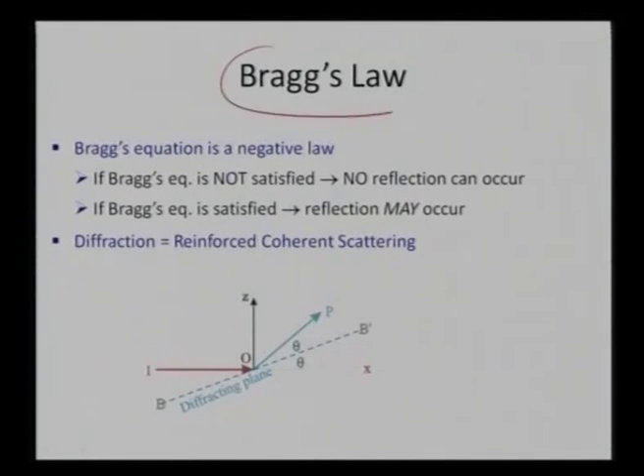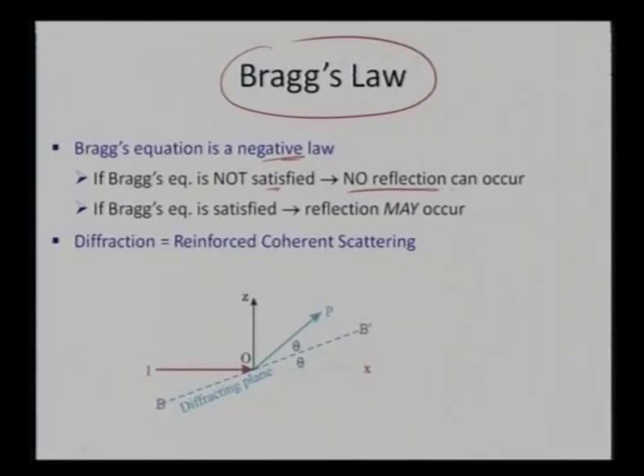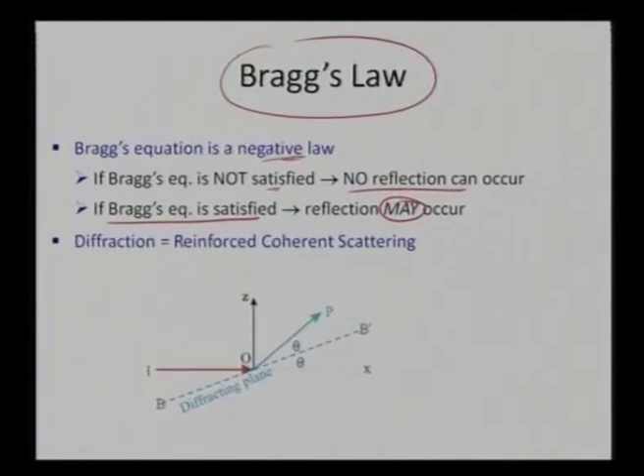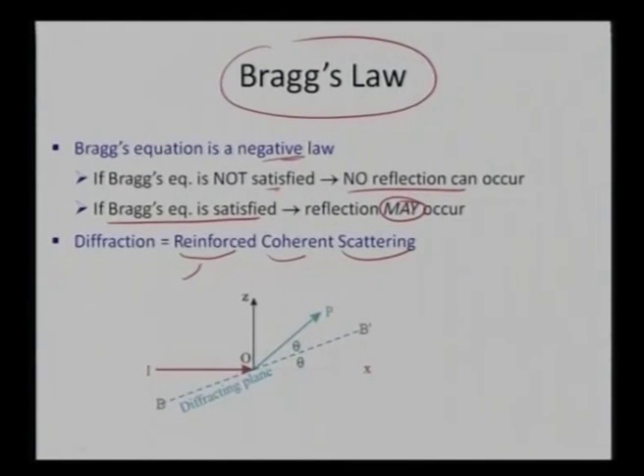Bragg's law is not a positive law; it is a negative law. If I am not satisfying Bragg's law, no diffraction will occur. Once Bragg's equation is satisfied I may see diffraction, which is defined as reinforced coherent scattering — reinforcement of coherent beams which are scattered.